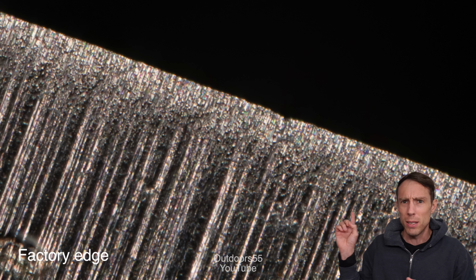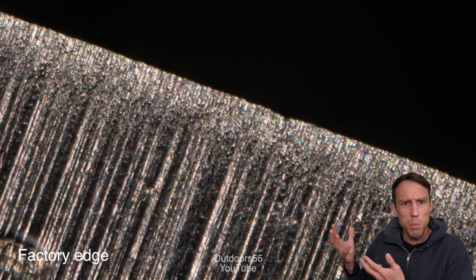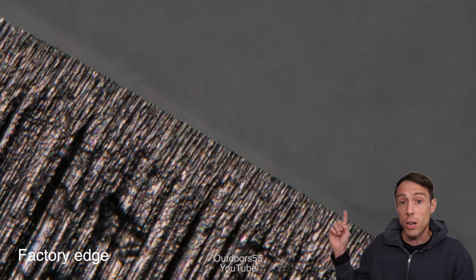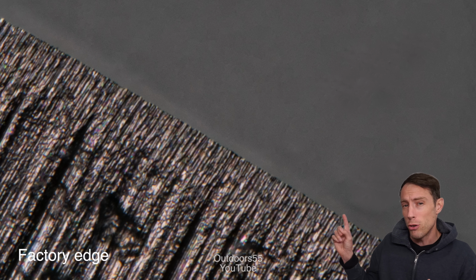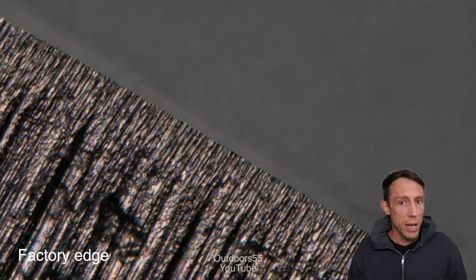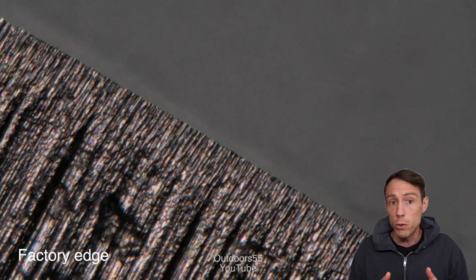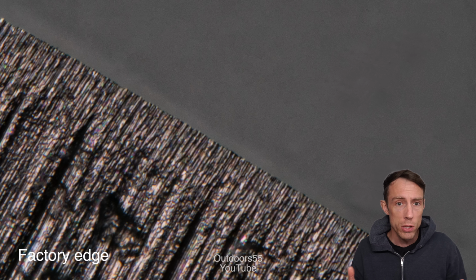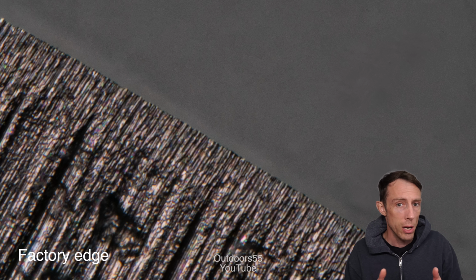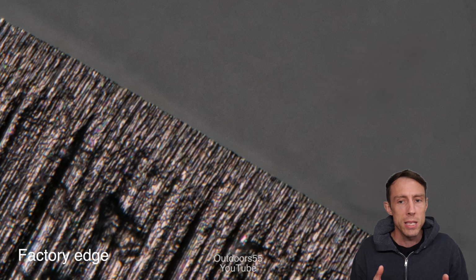We have a lot of these little kind of weird dots poking out of the steel. These are the carbides, while the surrounding steel matrix has been somewhat worn away. Now this tells me that these knives were most likely not sharpened on diamond, since whatever abrasive was used wasn't really hard enough to cut or abrade the carbides at the same rate as the surrounding steel matrix. More on this in a minute.